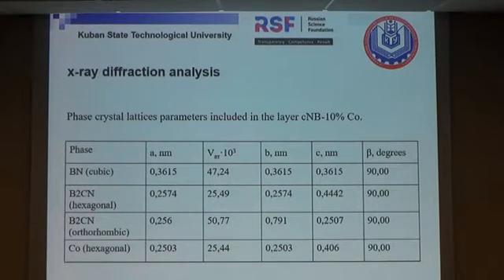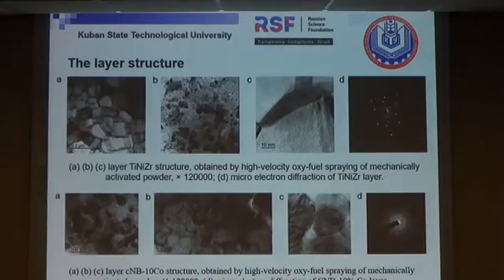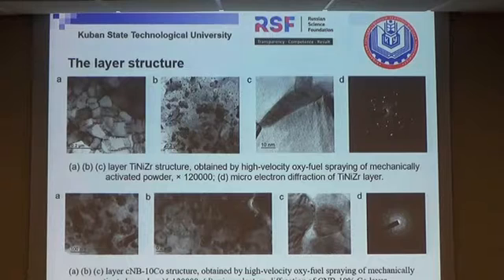The table shows the parameters of the crystal lattices of the phases within the layer, cubic boron nitride with 10% cobalt. Due to the characteristics of high velocity oxyfuel spraying of mechanically activated powder, in the cross section of the titanium nickel zirconium layer there are no distinct dendrites. The structure can be characterized as a nanoscale one. The resulting titanium nickel zirconium layer has a nano-sized structure.